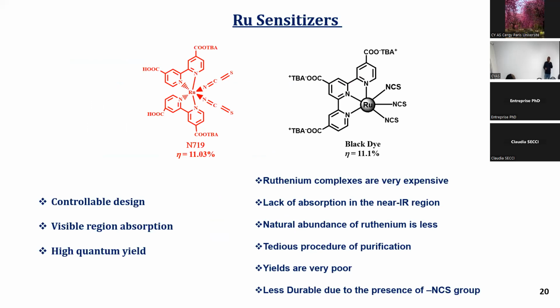In the initial days, for DSSC application, they used ruthenium sensitizers. Ruthenium sensitizers N719 and black dye were used. They reached an efficiency of around 11%. N719 dye reached 11.03% and black dye 11%. This efficiency is good, but some drawbacks are there.